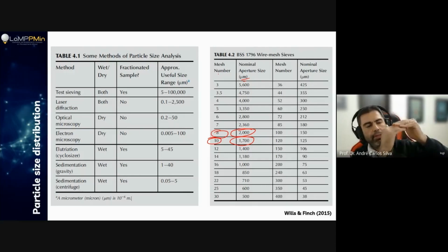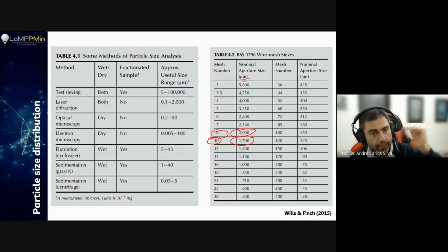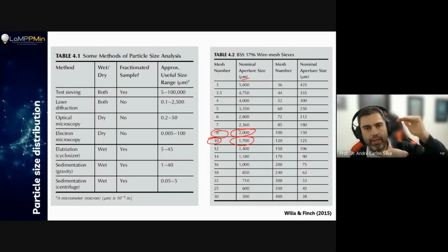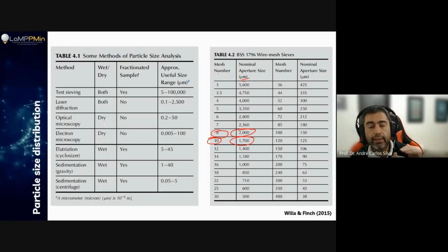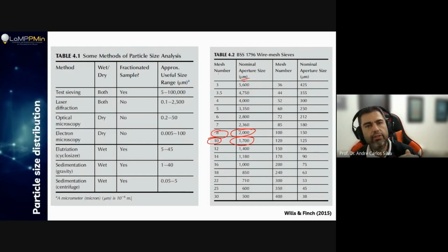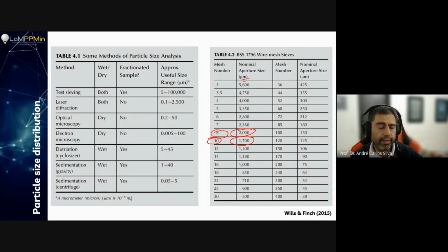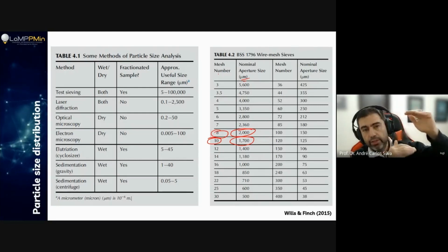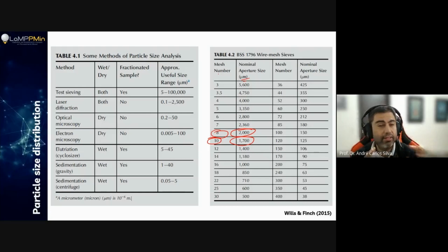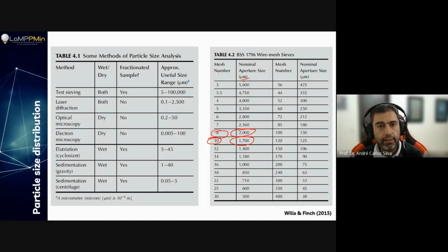So if I go there and put 9 sieves, after the test I have material fractioned in 9 parts. And I can perform the chemical analysis of these 9 parts of my material. That's what I call chemical and granulometrical analysis, and I call this granulochemical analysis. So what is a granulochemical analysis again? I take the material, I go to the sieving, I separate the material according to the size, and then I analyze chemically the material according to the size. And that's one of the most important tests that we perform daily in my lab here in Brazil.